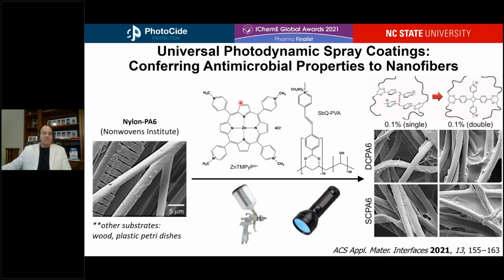So what we did was we took the bicomponent mixture, placed it in a simple airbrush, but you could do this with dip coating, kiss rolls, any type of coating technology, slot die coating that you'd be interested in using on an industrial scale. And we took from the NC State Nonwovens Institute nylon PA6 nanofibers that were made in the same fashion as polypropylene nanofibers would be made for use in N95 masks, as an example.